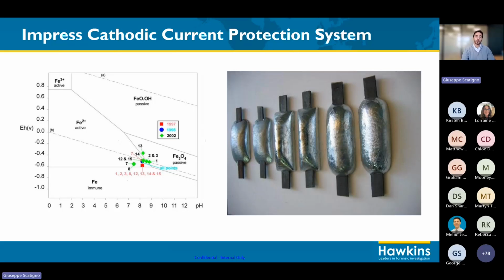And on top of that, we impress a current. Now, what you can see here on the left-hand side is effectively kind of a visual guideline of where you might be passive, therefore you might be protective, and where you might not be protective, which means that your hull is actively corroding, releasing ions into the sea. And by applying a current, we can effectively move up and down this graph, putting our metal in a situation where this is protected from corrosion. However, if this is not done correctly,